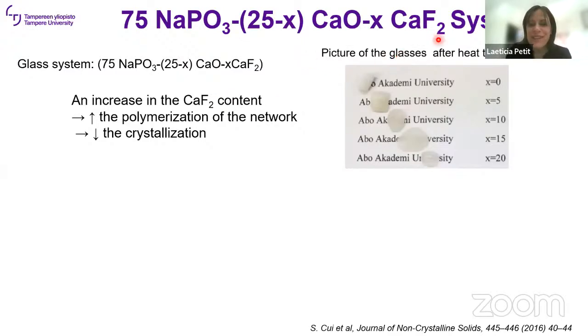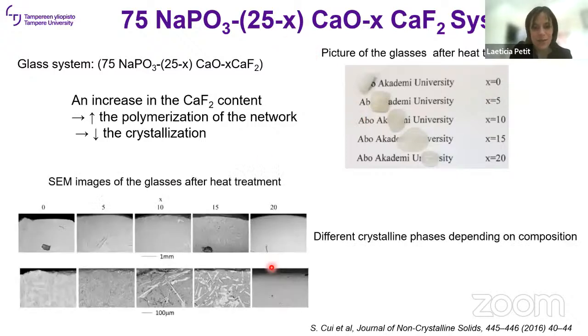And you have here the picture of the glasses after heat treatment. And we found that depending on the glass composition, we don't get the same type of glass ceramic. So we found that an increase of the calcium fluoride increases the polymerization of the network and decreases the crystallization tendency of the glass.